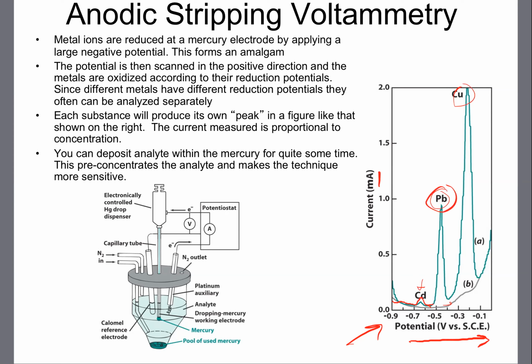Now these materials were originally present in our sample. So why are we seeing peaks for them now? Well, what happened is in that first step, which is called a pre-concentration step, we accumulated the cadmium, lead, and copper, which was dissolved in this solution, into the tiny mercury drop. We reduced those metals into the mercury drop where they form this amalgam or metal mixture, okay? We just collected them there.